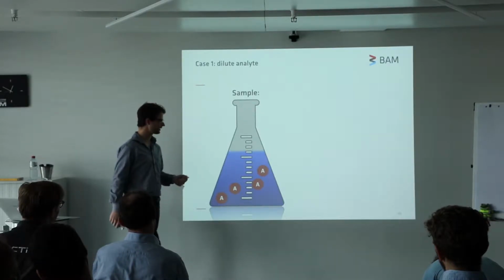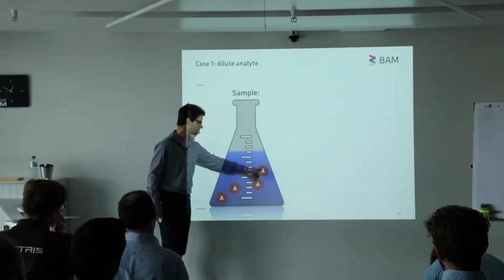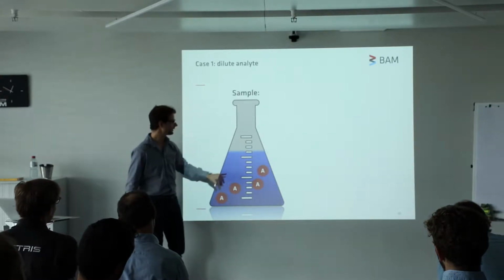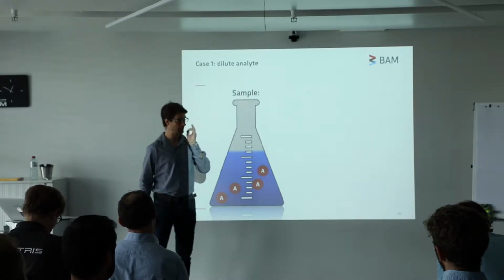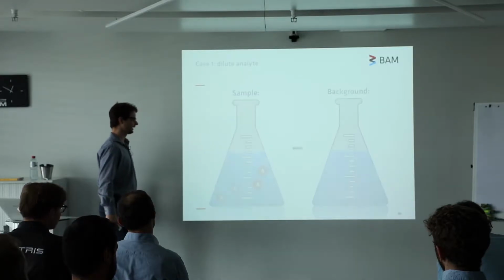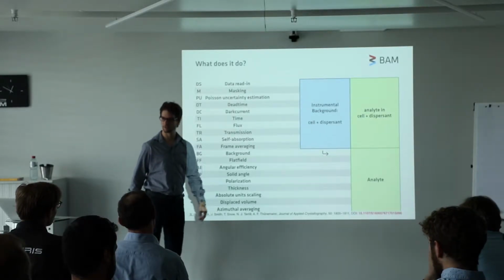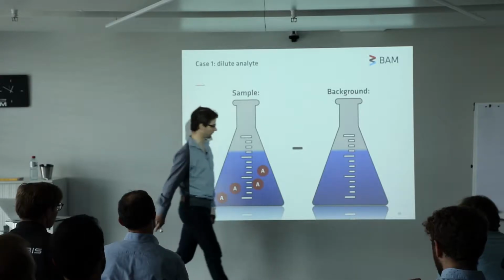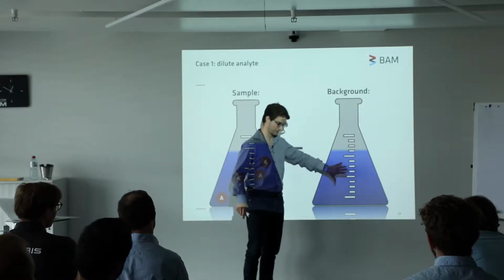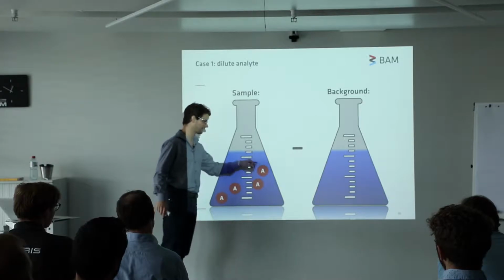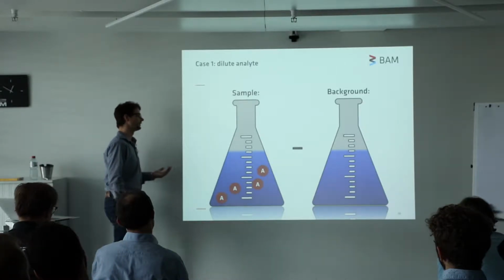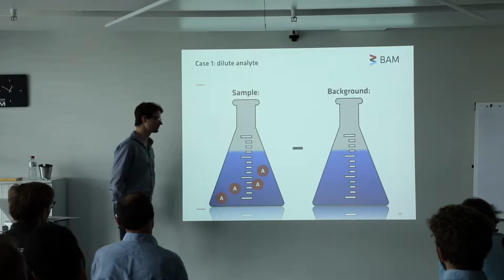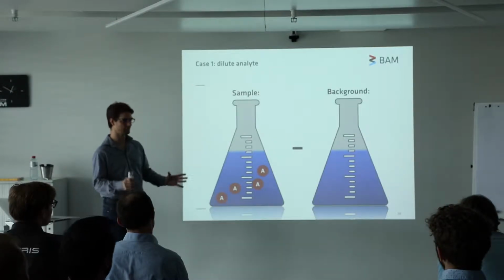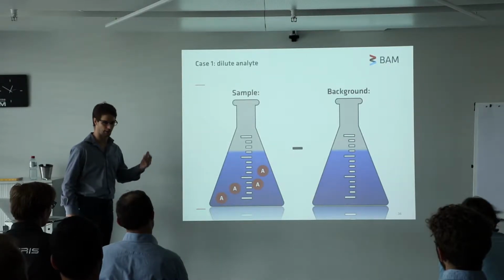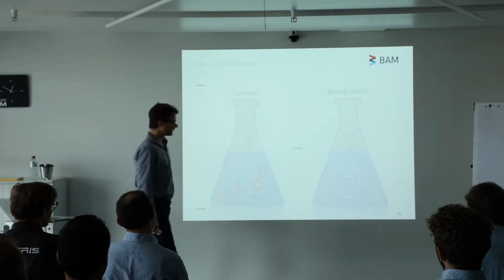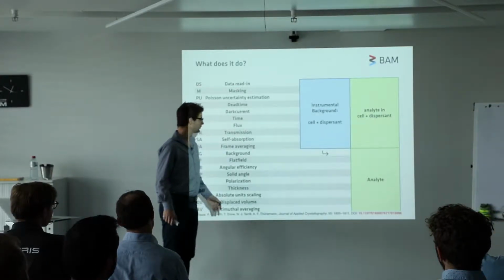In that case, you can measure your sample, which is usually an analyte dispersed in something, inside a container. From that, you would subtract for your background the container with the dispersant in it. Now, this dispersant has to be as close as possible to this dispersant. So if it is a buffer of any sort, then please measure that buffer. Even water can be different depending on how hard it is. And then you do all of these corrections.